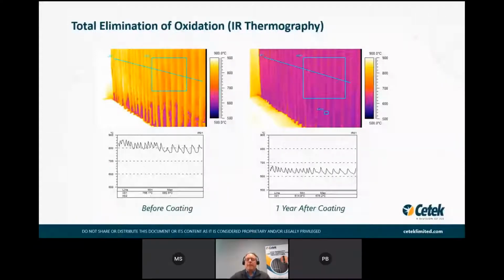Now this is a significant barrier to conductive heat transfer, and all that does is raise your CO2 and your NOx emissions. But after coating, if you look at the shot on the right, the thin film ceramic coating stops oxidation. The IR shot shows that the coating provides a much lower barrier to conductive heat transfer. Now the delta T between the tube metal temperature and the surface temperature is more like 40 F or 20 C. So at the end of the day, this is exactly the improvement you want in your fired heater efficiency. This would be about an 8% fuel savings, an 8% CO2 savings, and about a 15% NOx reduction also. All of that folds into exactly how the coating is going to perform.